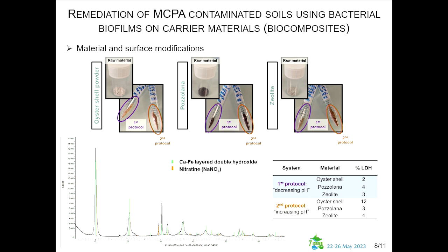Let's talk about the materials and the modification. Here you have pictures of the three materials: oyster shell, pozzolana, and zeolites. You have raw materials first, and then materials obtained after the modification, in an attempt to cover them with layered double hydroxides. The first protocol with decreasing pH, so we started with the sodium hydroxide solution, and we added the calcium and iron solution to be able to form layered double hydroxides, or the inverse protocol for the second protocol. Here you can see the X-ray diffractogram of the phase obtained after we sieve the suspension.